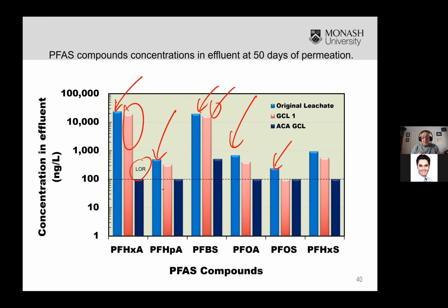But it does show you that the activated carbon has reduced the amount of PFAS going through the GCL. And it's not surprising, because there's a lot of work on activated carbon which shows that it is very effective in absorbing PFAS, especially the long chain ones, through these hydrophobic interactions. And it seems to be the case in the current investigation.